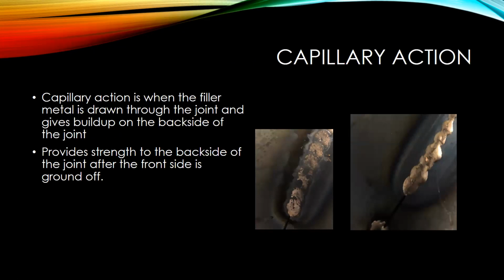So what the capillary action is in the pictures over on the right, I just did a quick weld this morning on some steel plate that I had, or some sheet metal. And so this is the top side of the weld. And what that capillary action is, it's when that filler metal gets drawn through to the backside, and you can see that additional buildup on the backside in the picture on the right.